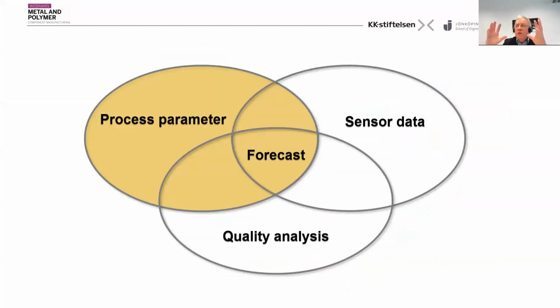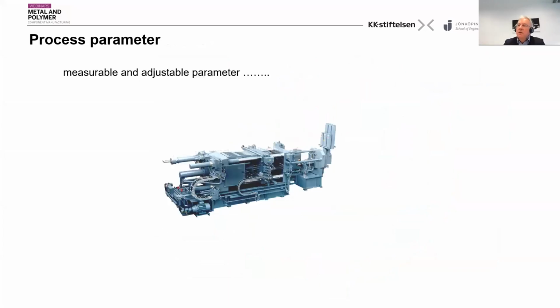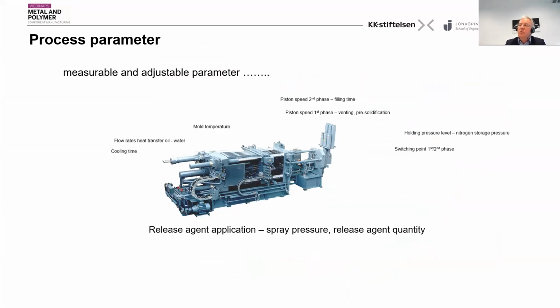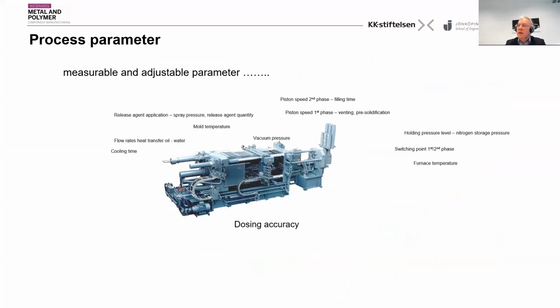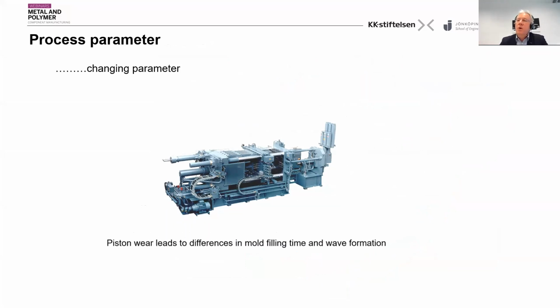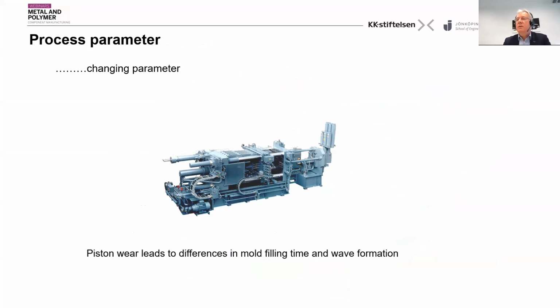So we have a lot of process parameters. Some people say 200 parameters in high pressure die casting: piston speed, first stage switch points, holding pressure, mold temperatures, flow rates, cooling time, and so on. You can talk half an hour about every process parameter here. But also the other parameters I just showed, we think we can control them.